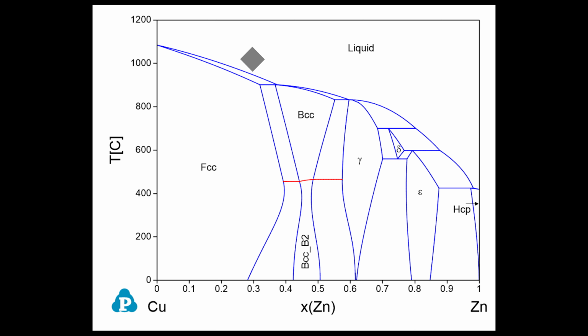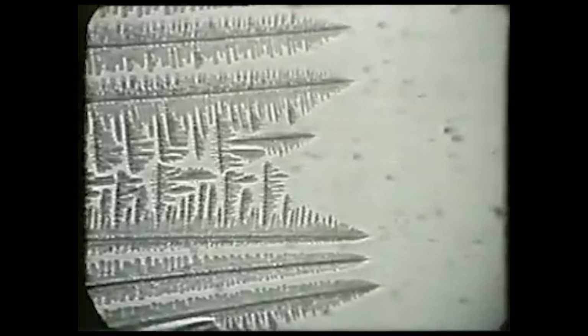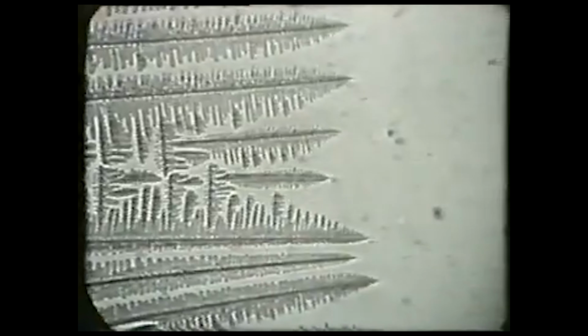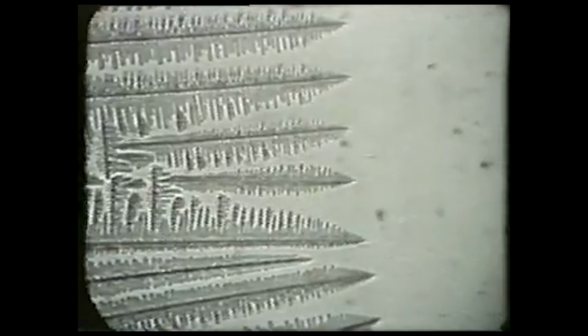What makes our copper-zinc alloy different is that the copper has a higher melting point, so that means it also has the higher solidification point and wants to solidify first when being cooled. So the first solids to form are copper-rich alpha brass. As those alpha copper-rich dendrites form, they absorb a higher ratio of copper to zinc than in the surrounding liquid, slowly locally increasing the zinc concentration. Eventually, a point is reached where the zinc concentration becomes high enough that the remaining liquid now starts to solidify as zinc-rich beta brass instead. And as this alpha to beta transition occurs at a discrete composition boundary, this dendritic solidification behavior is preserved rather than homogenized.